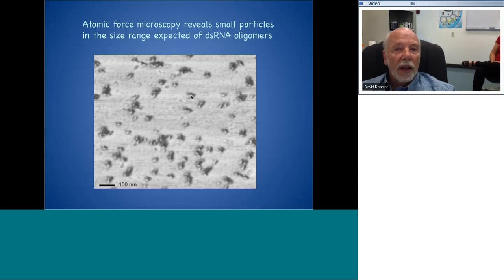Okay, I'm just about done. We did one atomic force microscopy so far. This is just on freshly split mica. You see lots and lots of little globs. They're down in the size range you expect for dsRNA oligomers. They should be about 30 nanometers long. And most of these little blobs that you see would be in that range. Occasionally they look like they kind of line up. We don't know what all that means yet, but this is not terribly surprising what we're seeing with atomic force.